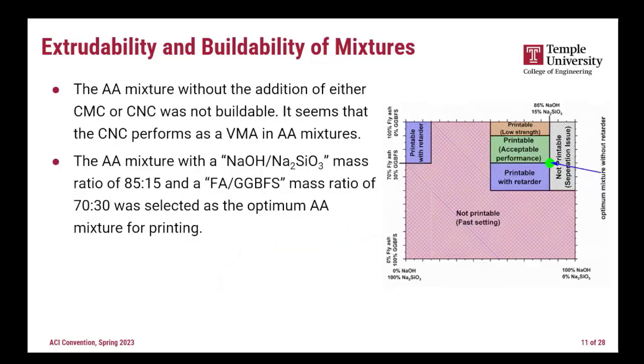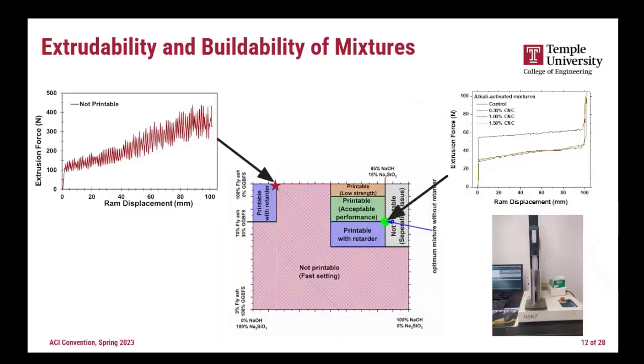Here's how we developed the alkali activated mix design. So you see the combination of the activator as well as the change in the composition of the binder. So we looked at which portion is printable with retarder, and where's the optimum mix. So you can see that here. And if we look at this by the pressure graphs, you see a non-printable system at the left side here, right? So this very high pressure requirement, and you have a hard time to extrude this through. And at the right side, these are the optimal mixes I mentioned.